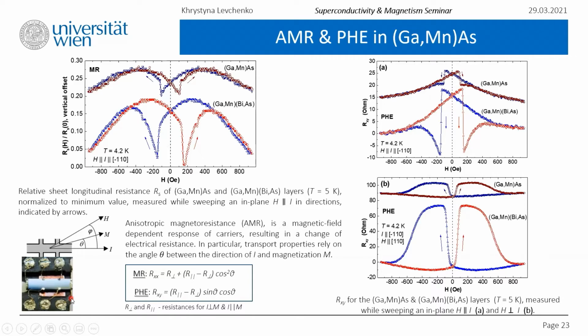The contacts in this case were done manually. Higher than expected Hall resistance values may be observed due to the non-ideal contact placements with respect to each other. This is the indium on the top of the sample, as well as the indium melted in the sample base. Both the contacts on top of the sample and base are connected via the golden wire. The base is then mounted in the sample holder. The coil is put on top. The wires are soldered, and the cold end of the sample holder with the sample inside is put into helium. And that's how we proceed with measurements.